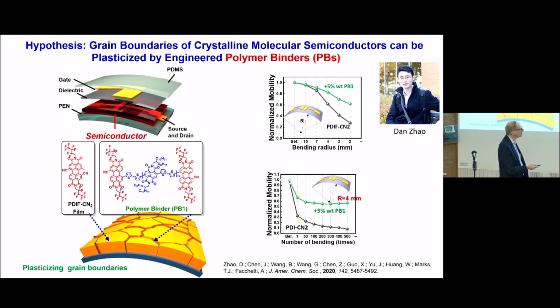And this polymer binder is just called PB1. So 5 weight percent, and you can see that the mobility drops a little bit as you bend it, but not as much as if you don't have the polymer binder.